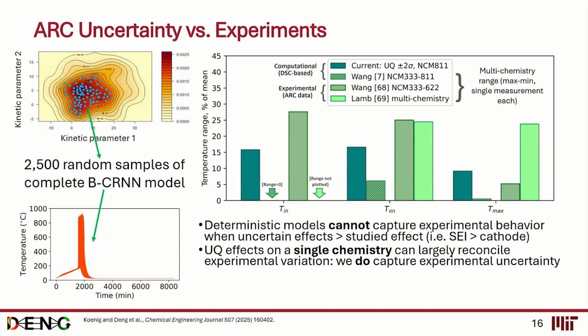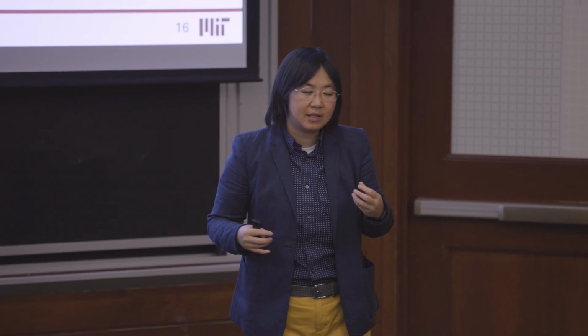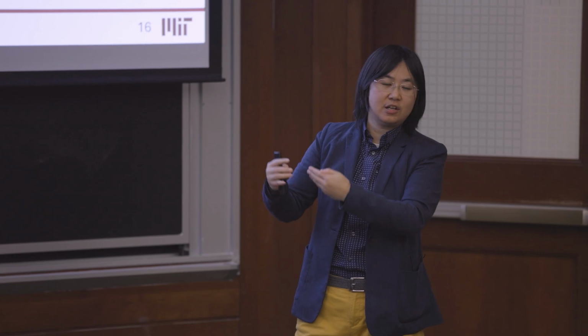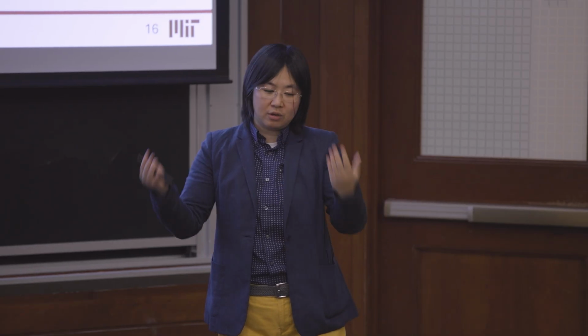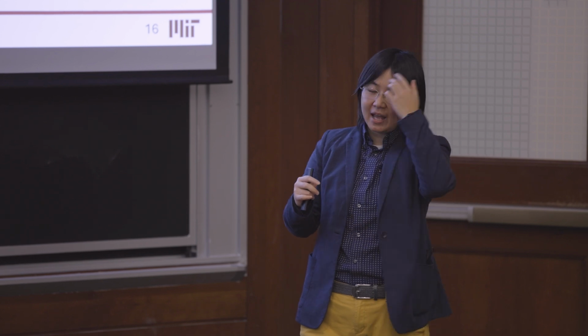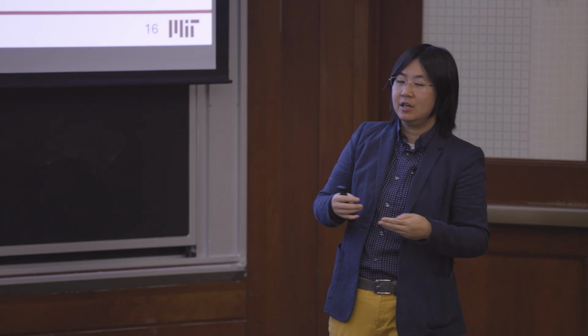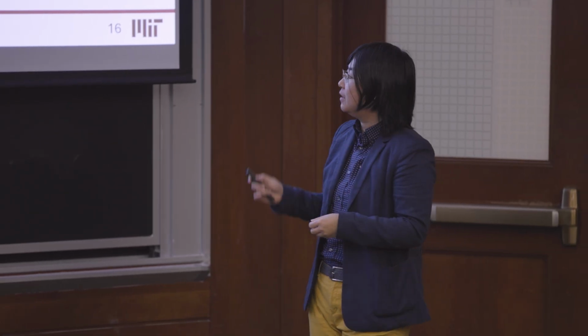So the take-home message is that due to the complexity of battery materials, sometimes due to the labeling of the manufacturers, but most of the time due to the usage of the batteries, you don't have pure materials. You don't have all the same SEI layers, etc. You do have a lot of experimental uncertainty. So when you come up with the chemical model to describe the dynamics, you actually need to consider such uncertainty. If you only take the deterministic one from a single experiment, you will not be able to capture the variations that we observe in the experiments.